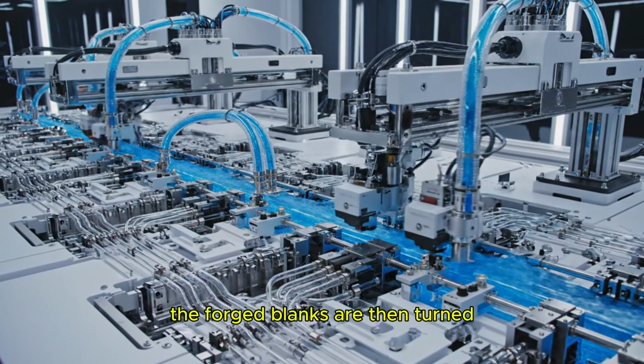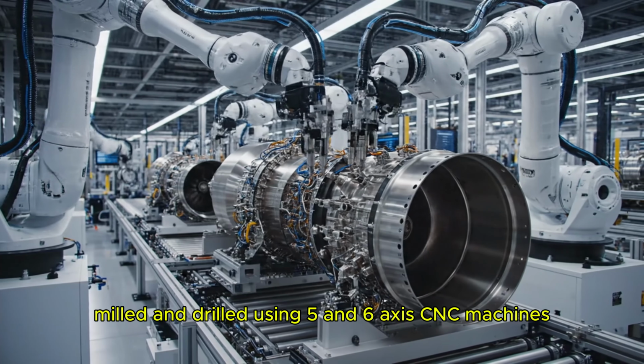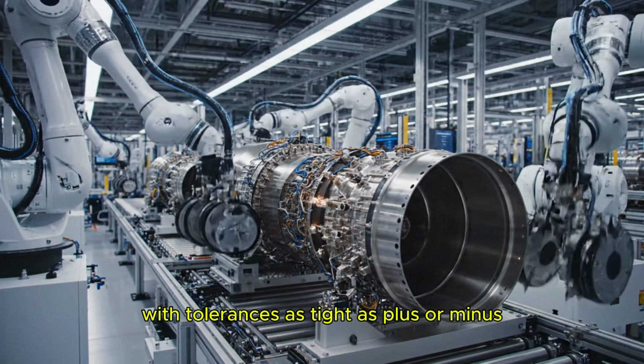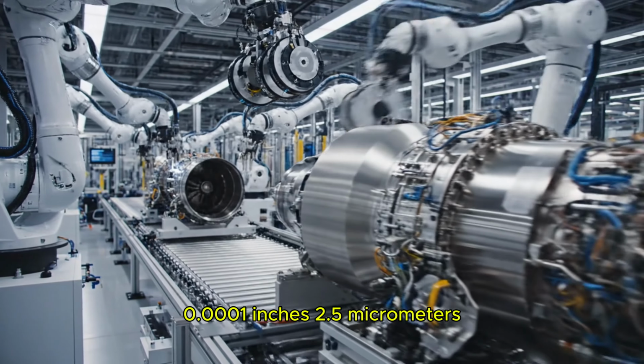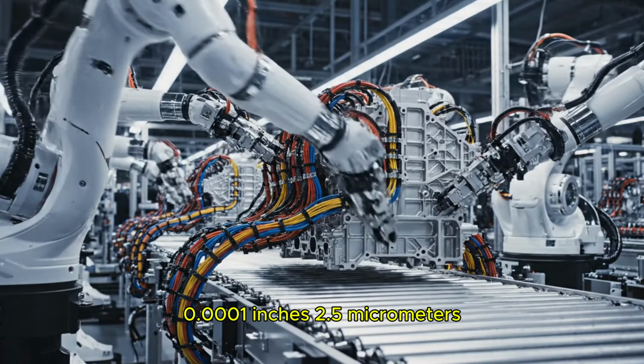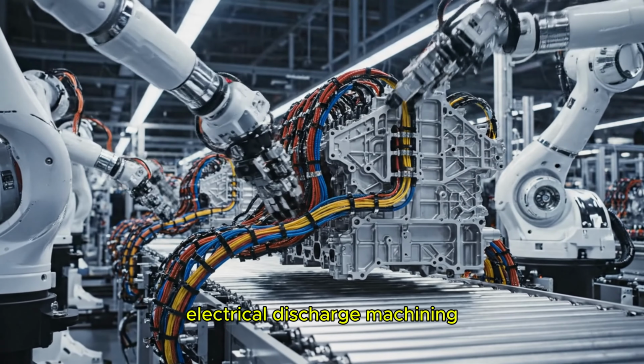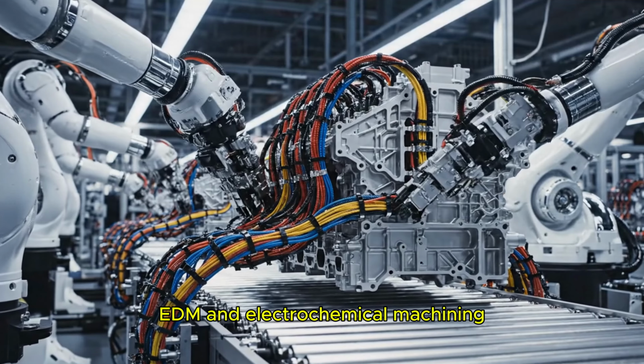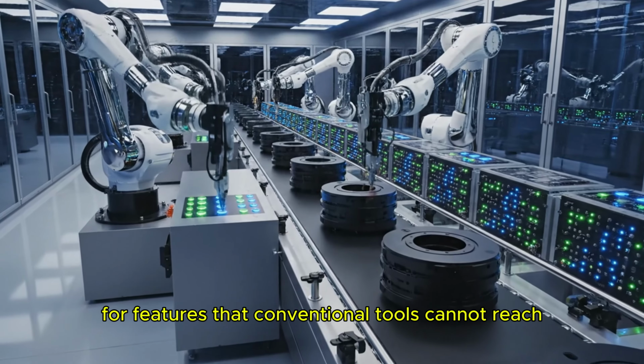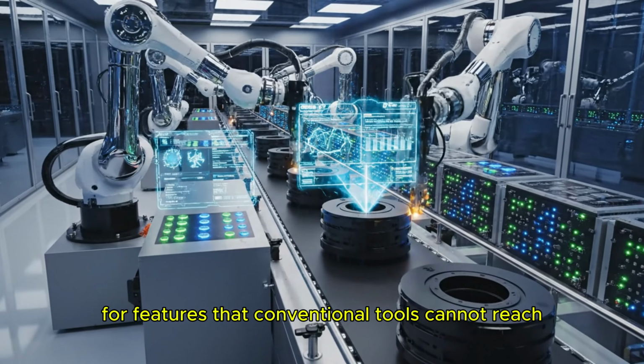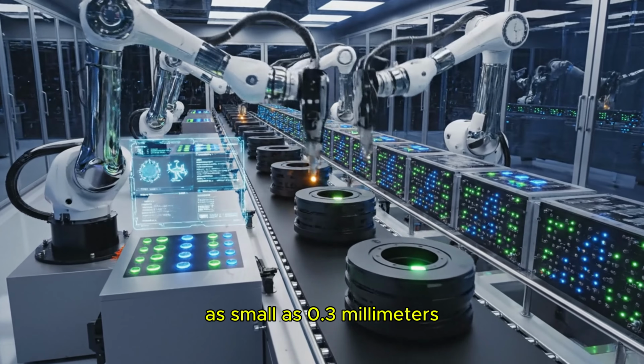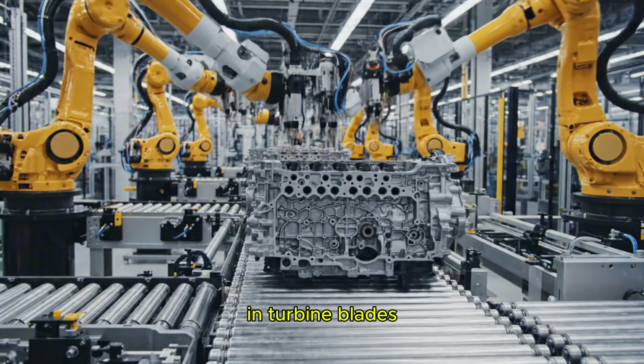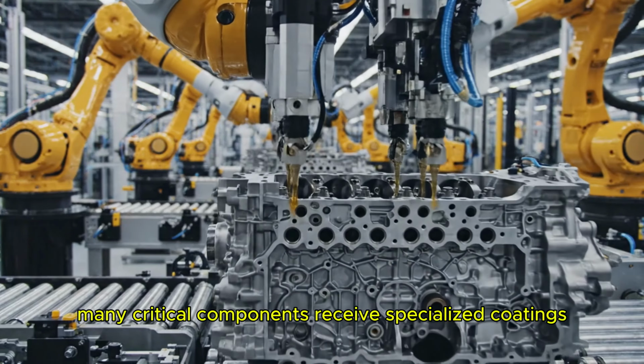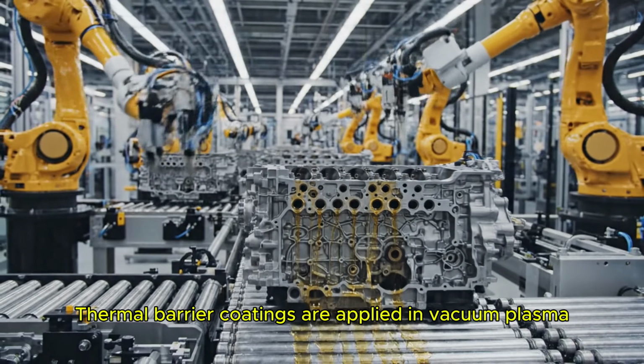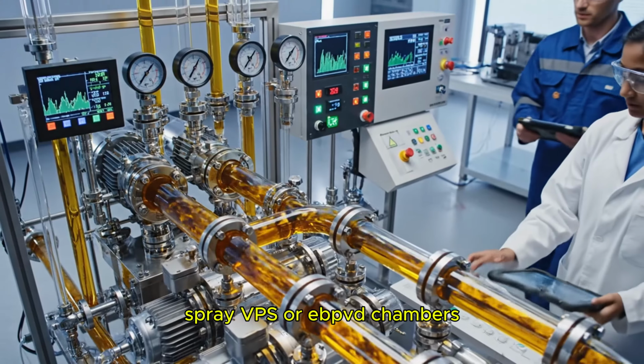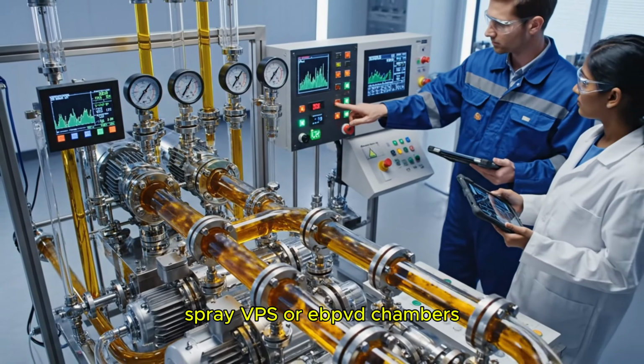The forged blanks are then turned, milled, and drilled using 5- and 6-axis CNC machines with tolerances as tight as plus or minus 0.0001 inches, 2.5 micrometers. Electrical discharge machining, EDM, and electrochemical machining, ECM, are used for features that conventional tools cannot reach, such as the tiny cooling holes, as small as 0.3 millimeters, in turbine blades. Many critical components receive specialized coatings. Thermal barrier coatings are applied in vacuum plasma spray, VPS, or EB-PVD chambers.